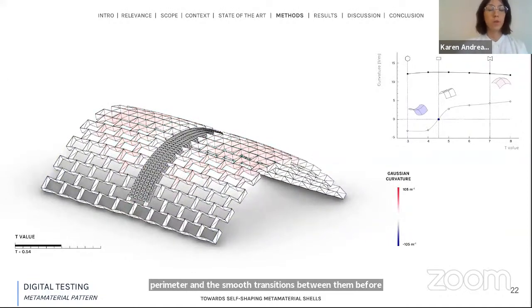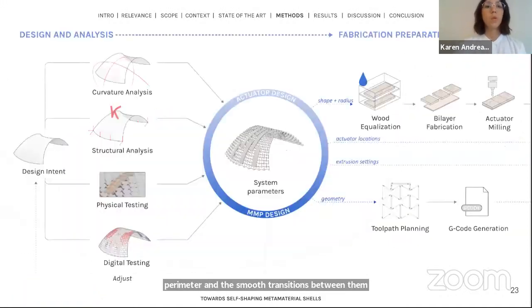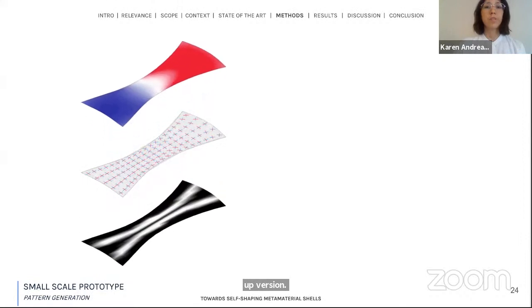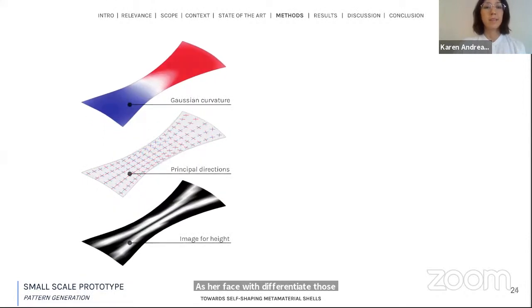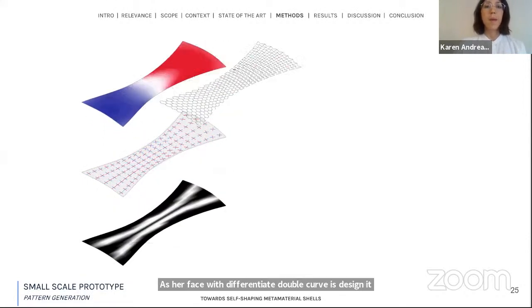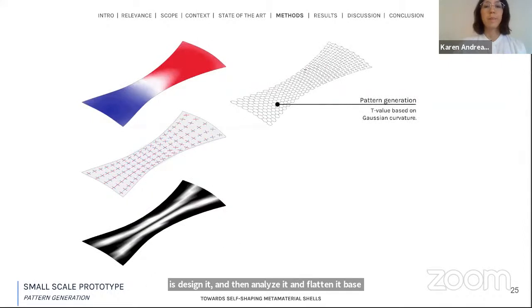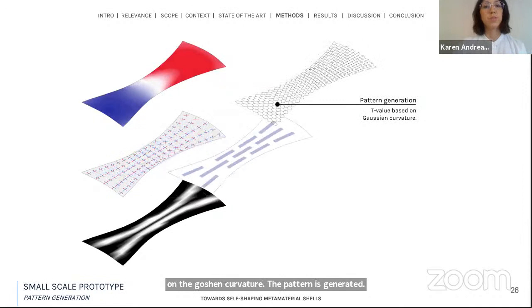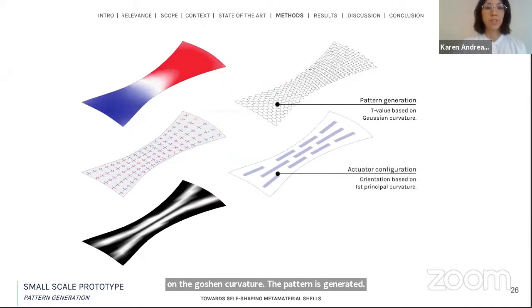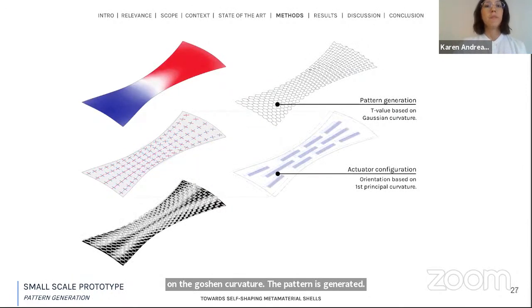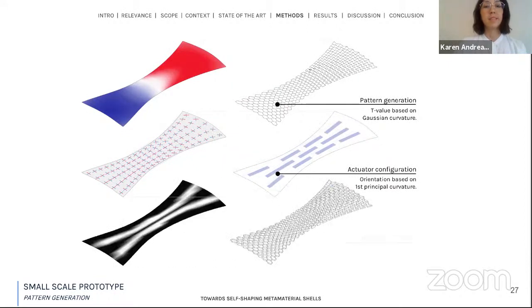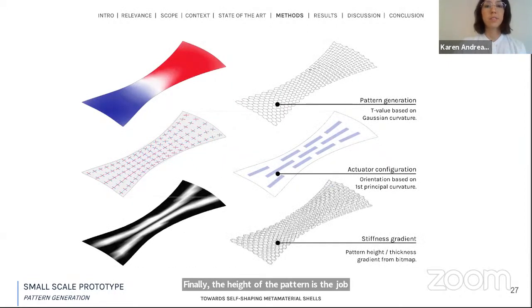Before testing the workflow on a large-scale prototype, we went through the steps with a scaled version. A surface with differentiated double curve is designed and then analyzed and flattened. Based on the Gaussian curvature, the pattern is generated. The actuator orientation is produced according to the main curvature directions. Finally, the height of the pattern is adjusted to reinforce it locally.